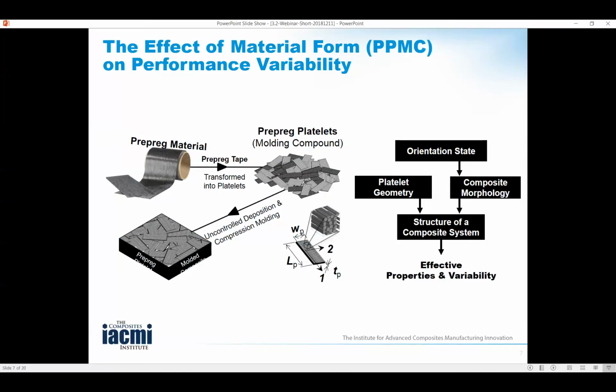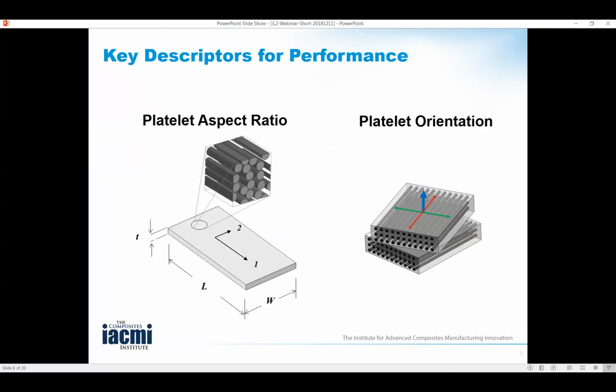In fact, Dow refers to it as a carbon fiber sheet molding compound that then is used to form structural parts. There are two key descriptors that we need to keep in mind when understanding this system. And the advantage of slitting and chopping this pre-preg is that you get a high degree of collimation, the fibers within a platelet, and you get a high fiber volume fraction.